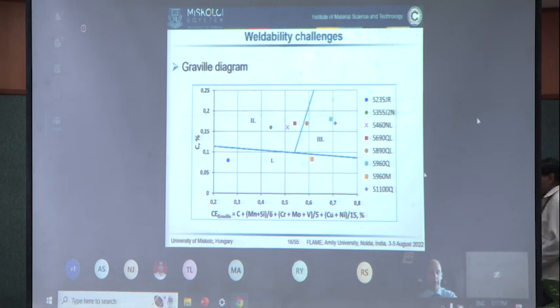If we consider quenched and tempered steels and TMCP steels of actually the same strength categories, if you see the 960Q steel, which is located in area 3, and if you consider the 960M steel, which is located in area 1, we can conclude that the thermomechanically rolled steel from the same strength category is less sensitive to cold cracking and therefore much easier to weld, even without the use of preheating.